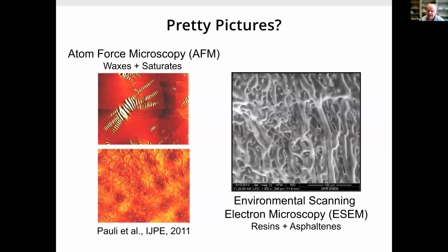When the asphalt binder cools down, these waxes tend to crystallize on the surface, and they can contract a little bit because what's underneath is still hot. So they contract and form this wavy structure, which shows up like a bee structure. These are nearly perfect crystals of wax molecules in the asphalt binder. Now at the bottom, you can see that it doesn't stop there. Around these initiation points, these seed crystals, when the binder cools down more, that shrinkage is not as efficient and you get less organized wax crystals, and they touch each other.